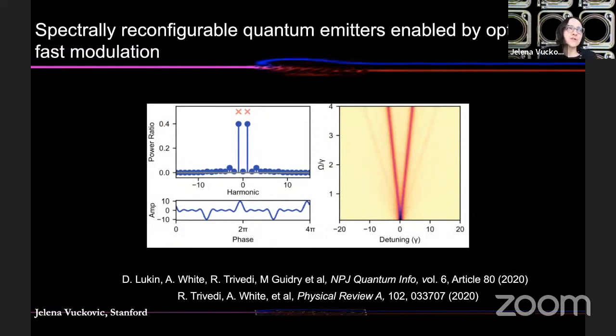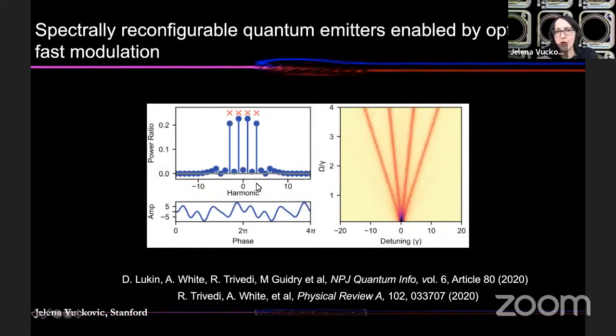What we would like to do is not just simple periodic drive, but optimized drive, meaning that you start playing with microwave drive, and of course that could also be optical drive, right? Some modulation on the laser for the case of Raman driving of color centers in diamond. But here we're talking about microwave drive, and we are kind of optimizing the driving signal in such a way that we produce a particular spectrum at the output, beyond a simple spectrum of Floquet eigenstates that you obtain for periodic driving. So if you start increasing these harmonics in the microwave drive beyond simple periodic drive, your spectrum at the output will also change.